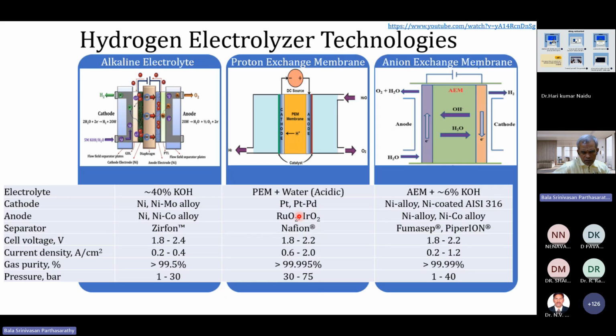On the other side, the PEM is very unique, uses water, and I put the word acidic here because some of the ingredients in what is called the membrane, some kind of reaction, leaching, leads to acidification, and the water becomes acidic. It should have a very high conductivity. Impurity levels should be absolutely nil, right? And they use quite a bit of expensive material. On the cathode, uses platinum and palladium, and on the anode side, even more challenging, expensive oxides of iridium and ruthenium for the OER, oxygen evolution reaction, to happen at the controlled condition. As all of you know, oxygen evolution and hydrogen reduction are the reactions happening at these two places when water is being electrolyzed.